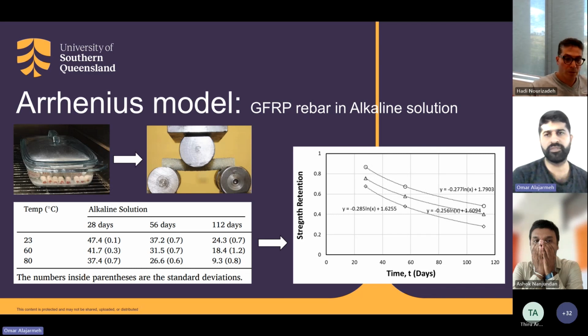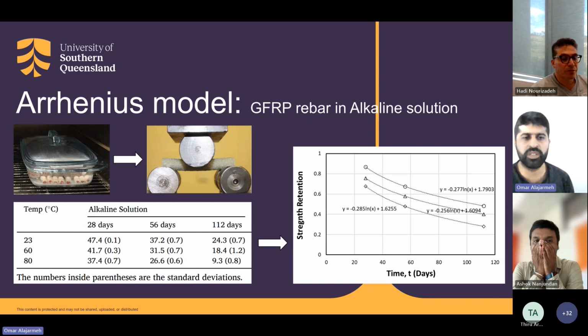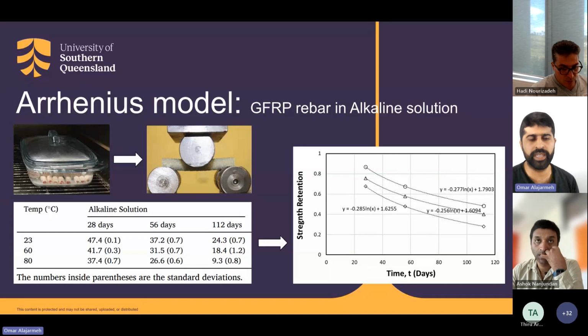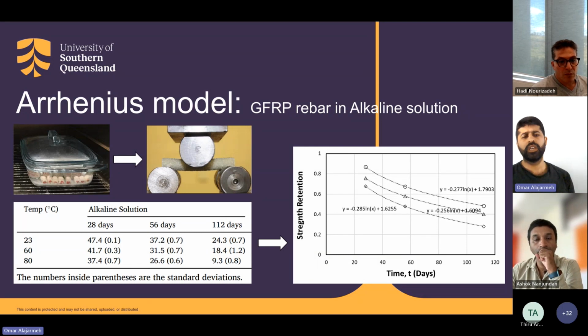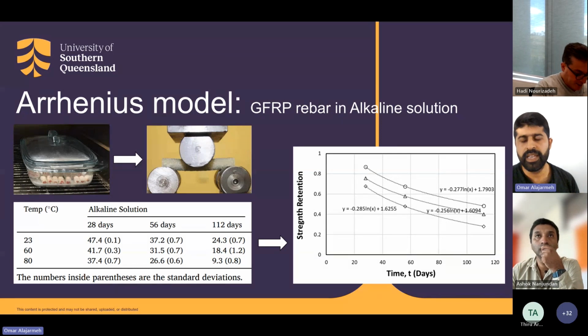We selected 3 to 5 bars to be tested to represent one dot point. The reference is tested at the beginning, and then we notice a reduction in the strength with the period, and a reduction in the strength when we increase the temperature. And here on the right hand side, you will see strength retention. Strength retention means we divided these values in the table by the reference strength of those bars, and we have seen that there is a logarithmic relationship of these test results with time.